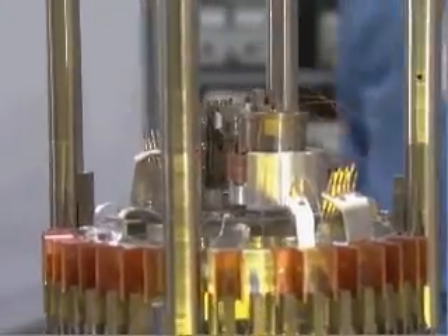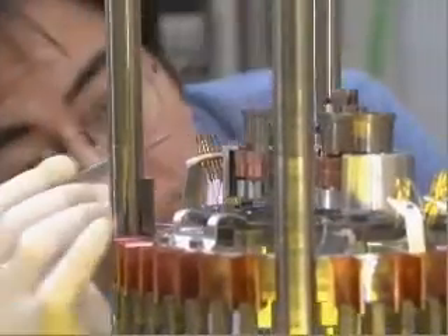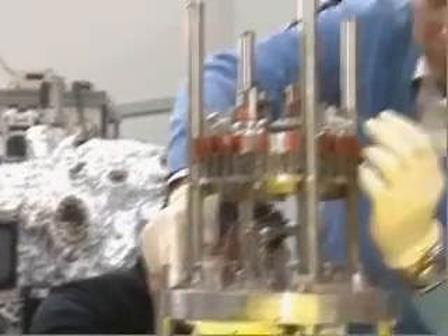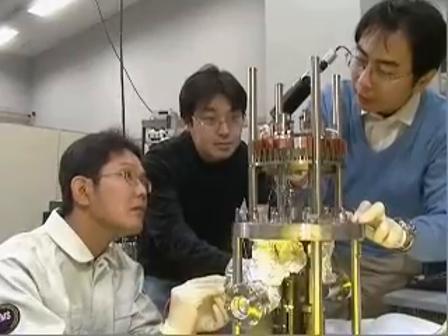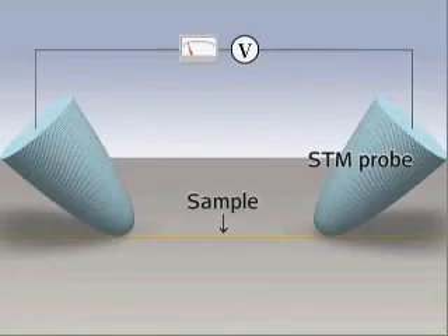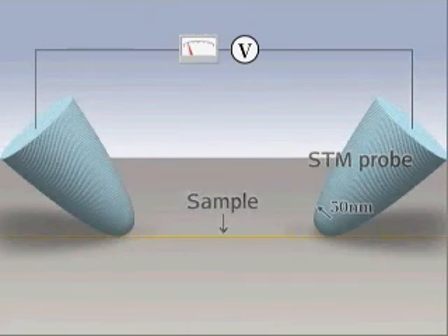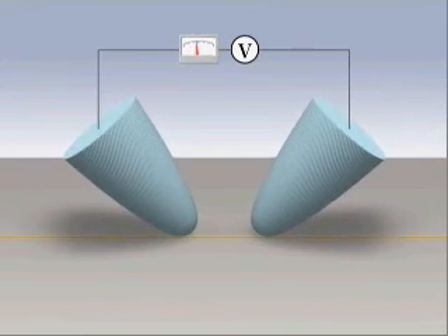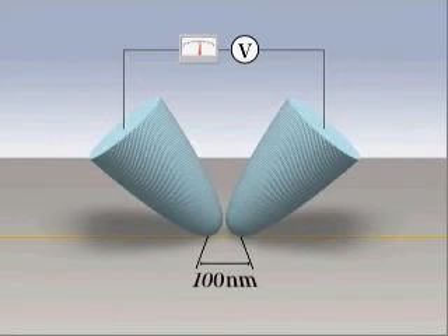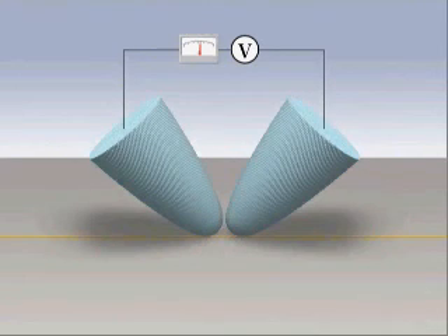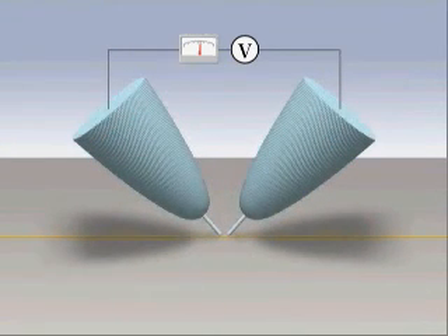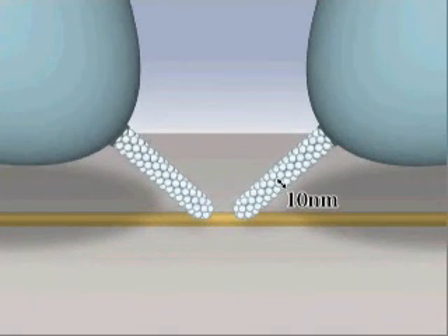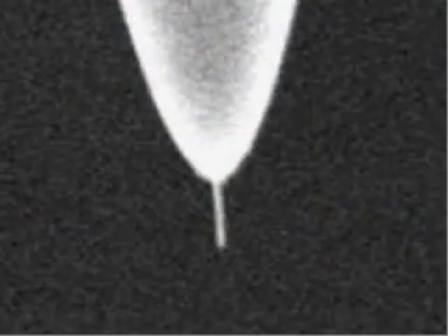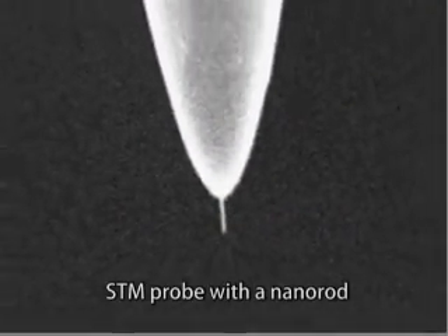Thus, the research team began working on developing a nanotester that uses STM tips as electrodes. The apex of a conventional STM tip has a radius of about 50 nanometers, and therefore two STM tips can measure a minimum distance of 100 nanometers. The research team overcame this issue and successfully created a double probe STM by growing a nanorod with a 10 nanometer radius at the tip of the STM.